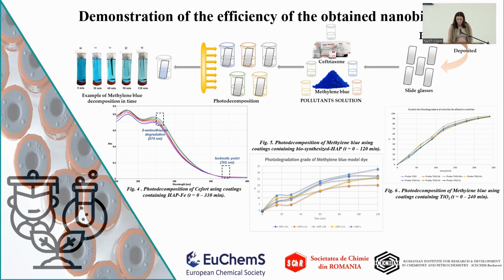As my colleague presented before, we tested coatings containing titanium dioxide in the photodecomposition of methylene blue, and we obtained 95% decomposition of this dye. But we all know that titanium dioxide is a well-known material for its photocatalytic activities. Also, we tested our biosynthesized hydroxyapatite material for the decomposition of methylene blue, and after 2 hours we obtained approximately 33% decomposition in the case of the simple biosynthesized hydroxyapatite, and almost 26-27% for the hydroxyapatite with iron and hydroxyapatite with cobalt.